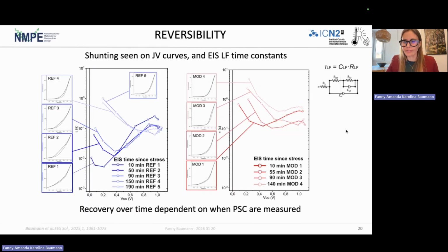So, a final remark about the reversibility is that we see, even on dark JV curves, that we could directly relate the changes in tau to the changes in dark JVs. So it was really valuable for us to be able to do different types of JVs in direct relation to the impedance spectroscopy measurements.